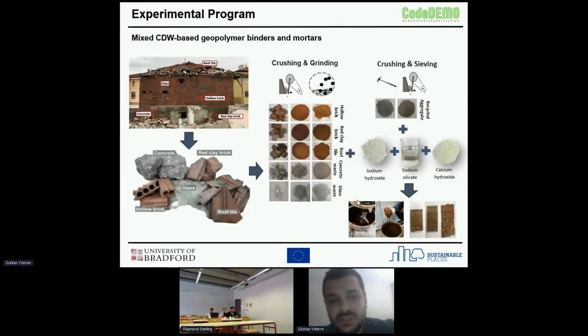So as a result of this selective demolition procedure, we collected hollow brick, red clay brick, and roof tile, and glass and concrete wastes. We crushed and ground them in laboratory conditions. And of course, you need to have a certain fineness to make these materials reactable with the alkaline activators you see on the right side, such as sodium hydroxide, sodium silicate, and calcium hydroxide. Then we add recycled concrete aggregates, after crushing and sieving, into these geopolymer binders to obtain the mortars and concretes in the final stage.